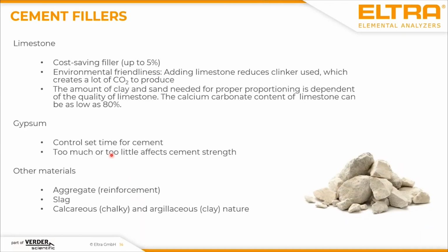Besides clinker, we have some other fillers. Most important is probably the limestone. It's cost saving, up to 5% is limestone, and the limestone is mainly made of calcium carbonate, but the calcium carbonate content is not very constant. It can be as low as 80%, but of course, to ensure production quality, it needs to be fixed. So the test of limestone is one of the main tasks of elemental analyzers in cement.